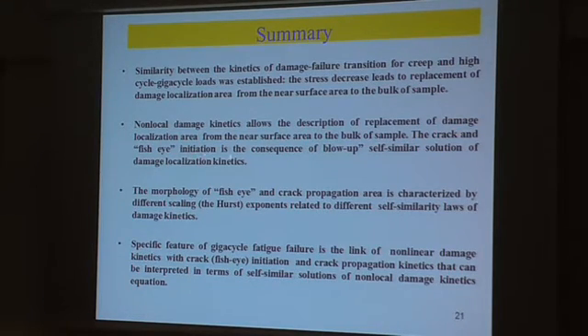The crack and fisheye initiation is a consequence of blow-up self-similar solution of damage localization kinetics. The morphology of fisheye area and crack propagation area is characterized by different scale in the Hurst exponents related to different similarity law of damage kinetics. Specific feature of gigacycle fatigue failure is the link of nonlinear damage kinetics with crack fisheye initiation and crack propagation kinetics that can be interpreted in terms of similar solution of non-local damage kinetic equations.